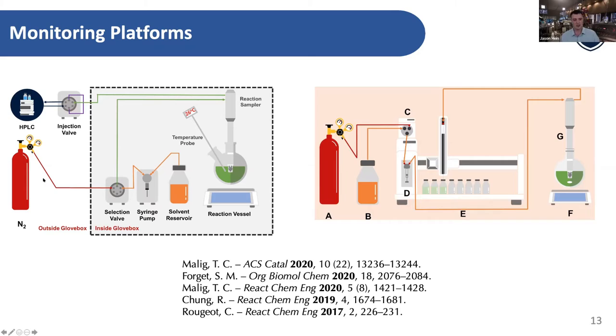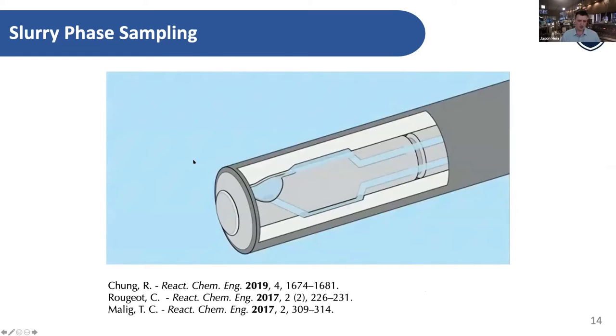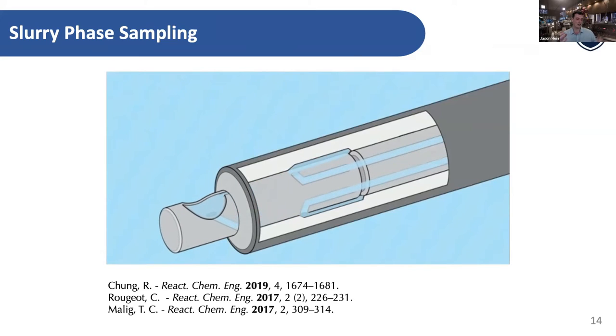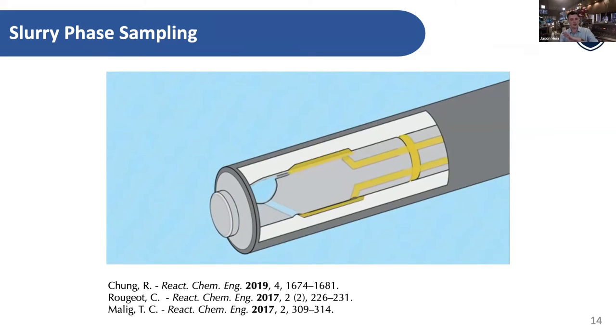Most recently was this deployment where a fully inert atmosphere could be coupled in an online way. A core piece of how this works is how the probe is interfaced. This is a piece of technology developed by Mettler Toledo, the probe part of it. What this probe does is allow us, with an electronic motor, to extend this sampling scoop. Passively, the sample enters that scoop, and we have the fluidic control in behind. So this is a sleeve valve. We draw that sample back inside the head, which allows us to then act on it.